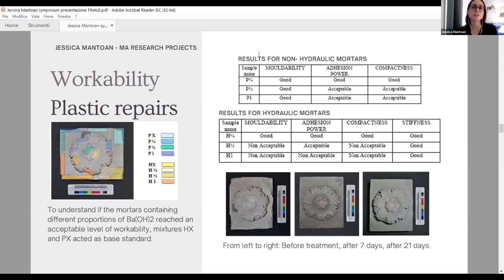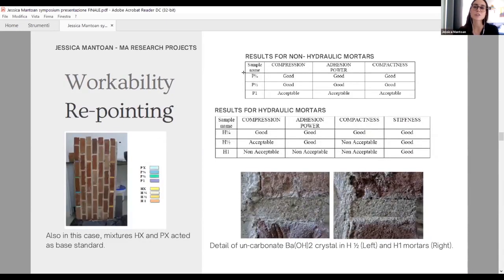On the opposite, the non-hydraulic mortars, all three types of mortar, resulted really good. In particular, the one with a really small amount of additive. Another workability test was carried out about repointing. So mortar was used to repoint areas of this wall. And as we saw before for the other workability test of non-hydraulic mortar, the results are quite good, and in the worst case, acceptable. While for hydraulic mortar, in particular, the samples with a large quantity of additive didn't show really good results.